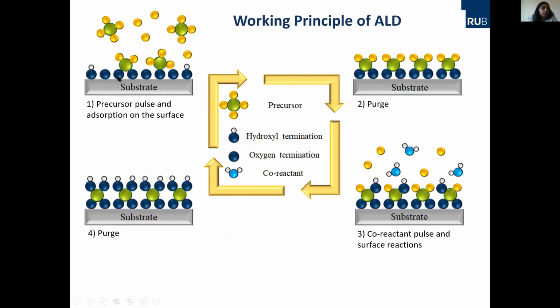So here you see, you have a substrate. Then you can think of hafnium chloride as a precursor. Then you see the hafnium metal center and four chlorines attached to that. So if you have a substrate, normally you have an oxygen or a hydroxyl terminated surface. So when this hafnium chloride interacts with the substrate surface, it will react with the chlorine and the hydrogen, HCl is released, and then the molecule gets bonded to the oxygen here. Now you have one pulse of the hafnium chloride precursor. Now when it completely occupies all the available sites, then you have some excess, and that is purged. So at some stage you pulse and then purge, and you have a monolayer of the precursor chemisorbed on the substrate surface.